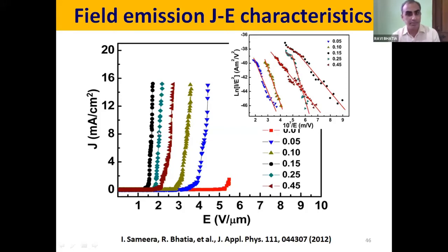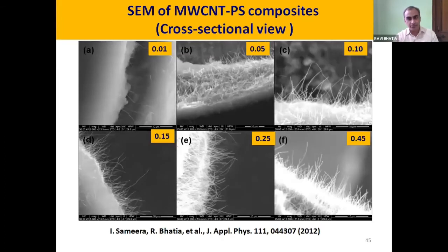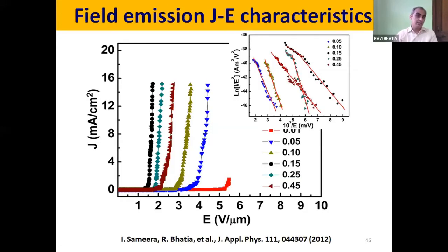Now again, there is a problem. We were thinking that if we keep on increasing the amount of CNTs within a composite, the protrusions are obviously going to increase, and when protrusions increase, the emission of current should be more in the case of the 45 weight% sample, because a large number of protrusions are available in the 45 weight% sample, which can be seen from the SEM images. So it is now a big problem why there is again a non-monotonic behavior of field emission properties in the case of composite samples.